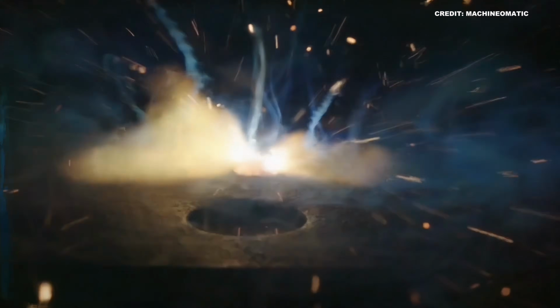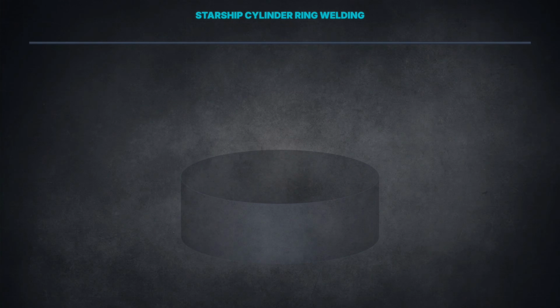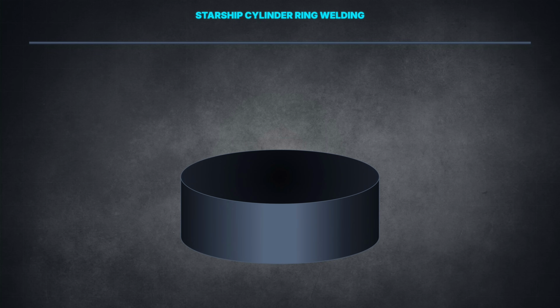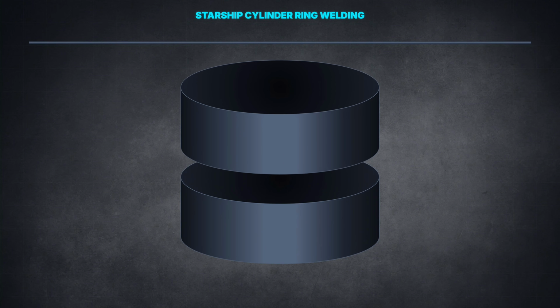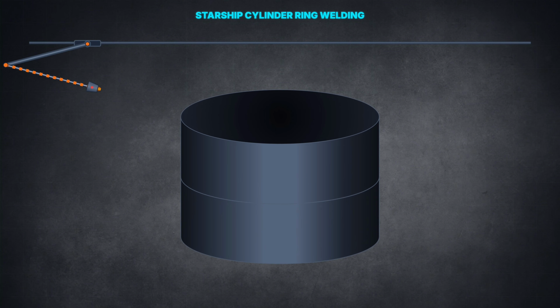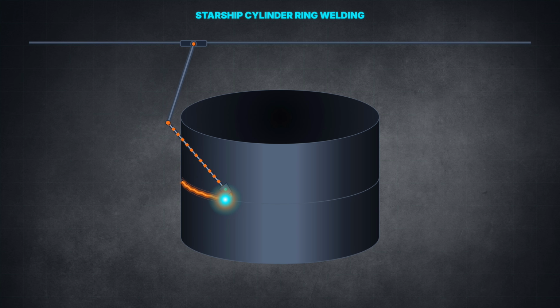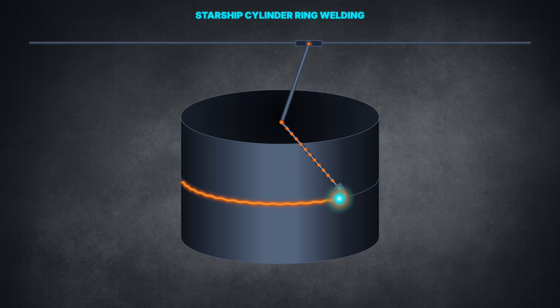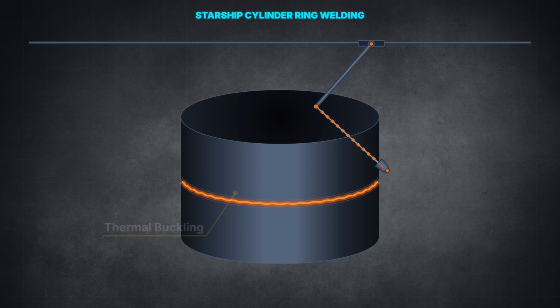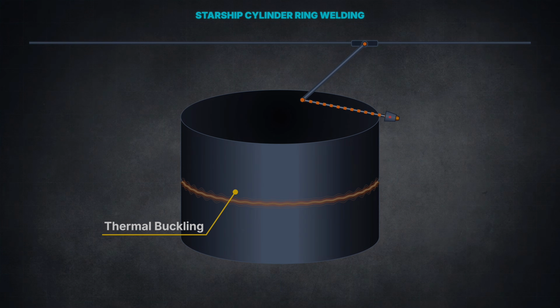Laser welding concentrates massive energy into a tiny spot. But this focus creates a sharp temperature gradient. Stainless steel has relatively low thermal conductivity, meaning heat stays localized near the seam. As this localized zone expands at 1,450 degrees Celsius, it pushes against the cold steel around it. This expansion causes the thin 4mm sheet to buckle, ruining the weld's alignment.